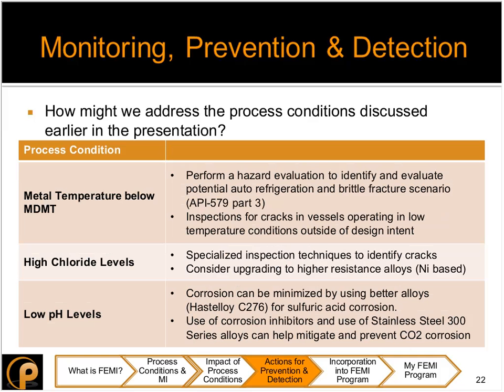For equipment that is operating below your MDMT, what you can do is perform a hazard evaluation to identify equipment that have potential auto-refrigeration and brittle fracture scenarios. And you can do some inspections for cracks that you might find when the equipment has operated below your MDMT, because cracks become the initiator for causing brittle fracture due to MDMT in many of these equipment.